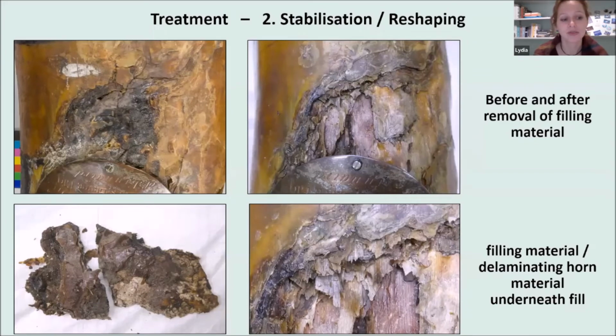During the conservation or the reshaping process, I encountered problems with the old fill I've mentioned before. These fills prevented a successful reshaping and realignment of deformed areas adjacent to the fill. When I had a closer look, I actually realized why. While the filling material was visually in level with the outer horn surface, it pressed the underlying remaining horn material inwards, causing distortions and tension in that area.